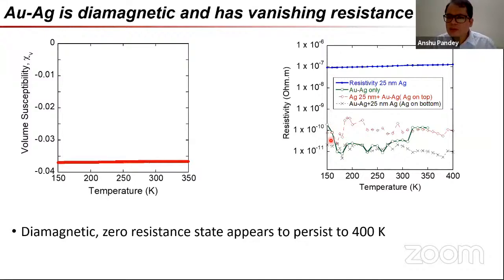The other point which we observed was that this material appears to have resistance which, as far as we could tell, seemed to be much below the resistance of a regular metal. So for example, in these units, the silver resistivity would be over here, as measured for a 25 nanometer film, while what we measured for AuAg was several orders lower. This, of course, can arise from any number of artifacts, but what was very compelling to us, at least at that point, was that it appeared that AuAg also had this ability to short out a silver film. So if we, for example, deposited AuAg on top of the silver film, it would actually lower the resistivity by these orders of magnitude.